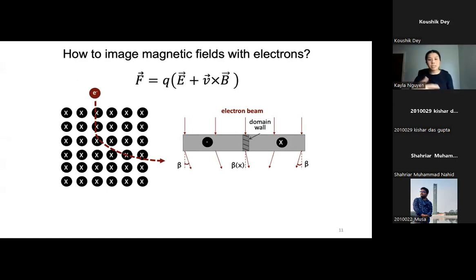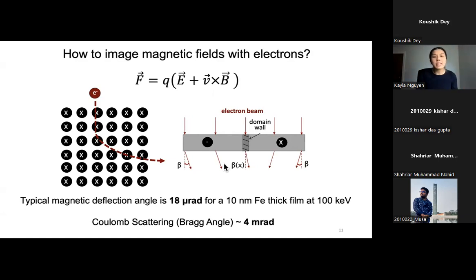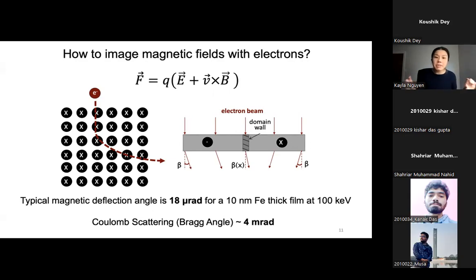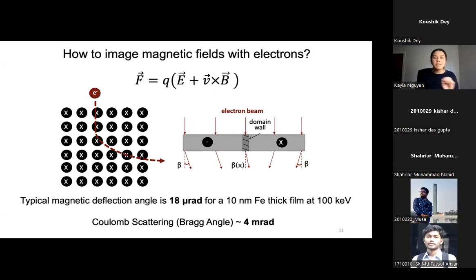And so then we go back to the Lorentz force law, where we have F equals q times (E plus v cross B). And so what happens is that your electron, as it scatters through a magnetic sample, gets deflected by the local magnetic field. And this deflection we can actually calculate. In an electron microscope, a typical magnetic deflection is about 18 microradians for a 10 nanometer thick iron film if we're using an electron beam that images at 100 kiloelectron volts. So this deflection is actually quite small relative to our Bragg angle, which is about 4 milliradians. So we're looking for a very small deflection compared to a crystallographic deflection.